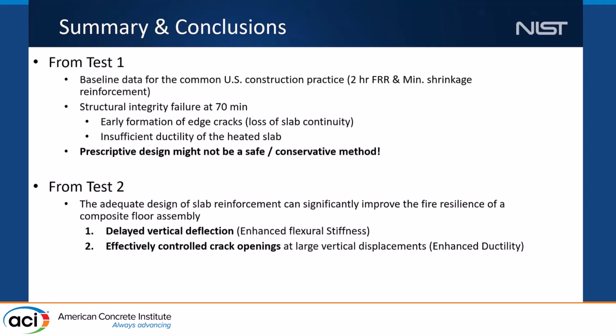Test number 2 mostly focused on the influence of the slab reinforcement, and how it improves the fire resilience of the composite floor assembly. With an adequate amount and adequate spacing of the slab reinforcement, we can delay the vertical displacement and also more effectively control the crack opening at very large vertical displacement.